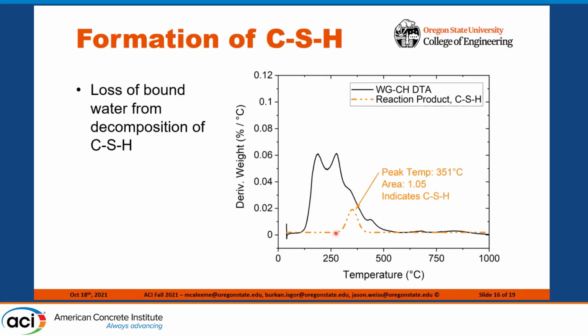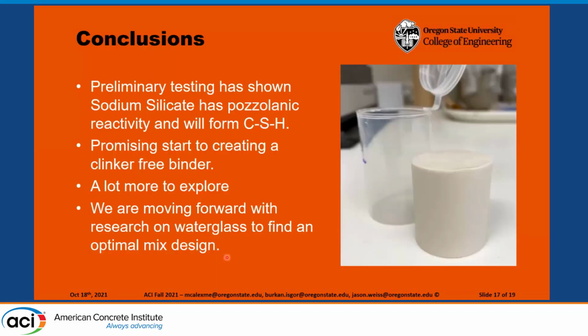The last peak also indicates CSH formation. The same reference found that the bound water of CSH is released between 180 and 350 degrees Celsius. The pozzolanic reactivity and CSH production show that the sodium silicate has potential to be used as a clinker-free binder. There's a lot more to learn about this system, but we're moving forward with testing, exploring different additions and mix designs to optimize a binder.